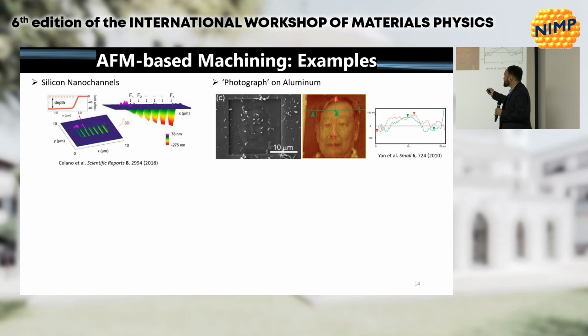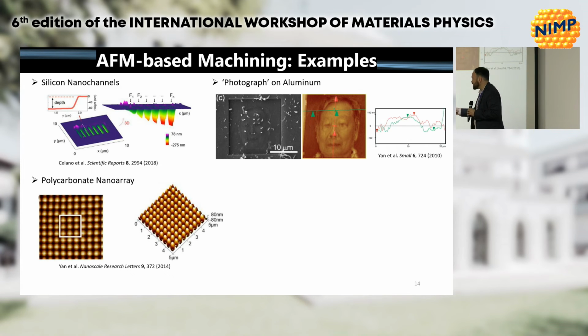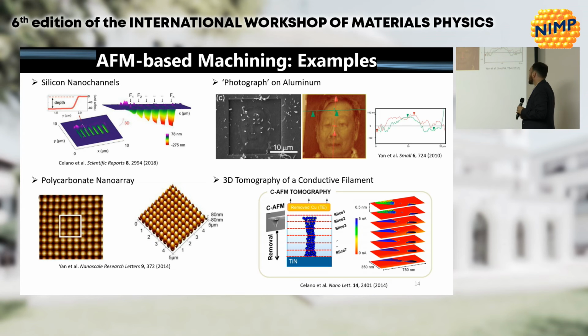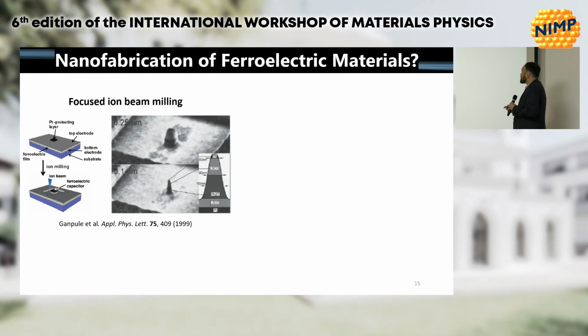Here's an example of transferring a photograph onto aluminium. Polycarbonate nanoarray. All of these are carved with an AFM tip. And this is an example of tomography, so measuring current as a function of depth. It's a destructive technique. You're removing material, but you measure the functionality each time. And the basic idea behind this is maybe there's a place for it in ferroelectric lithography.